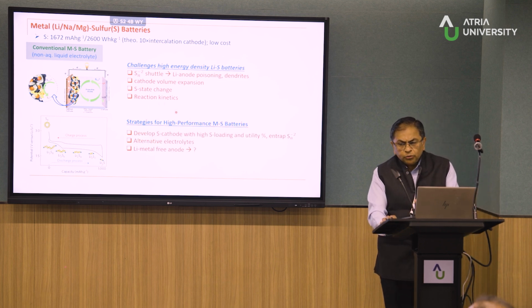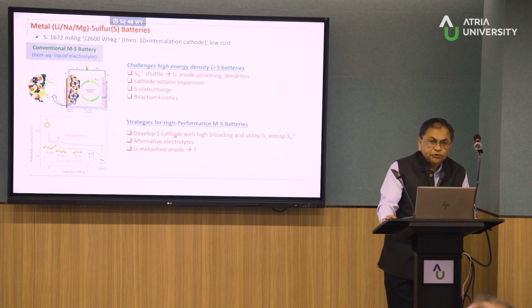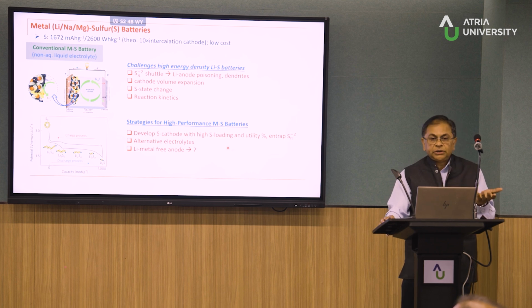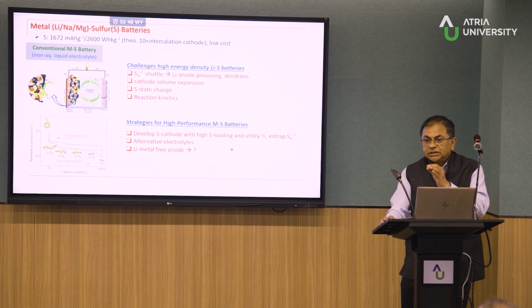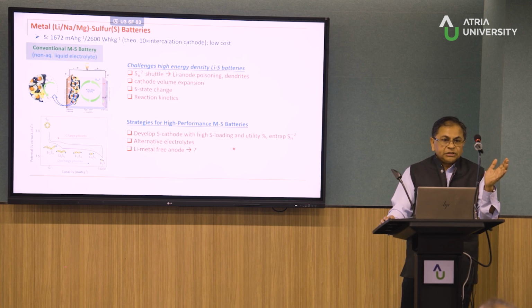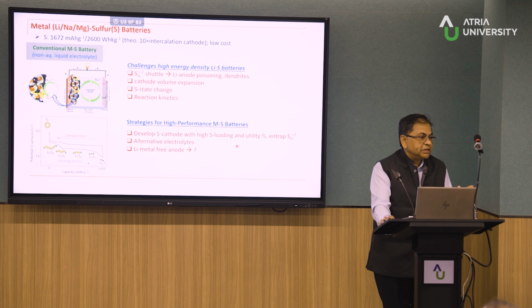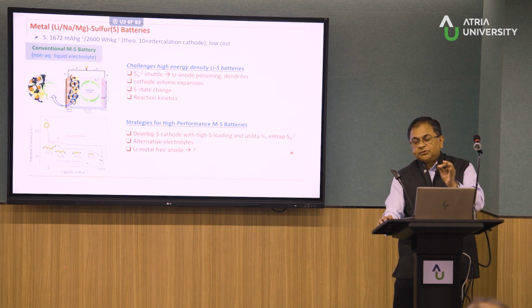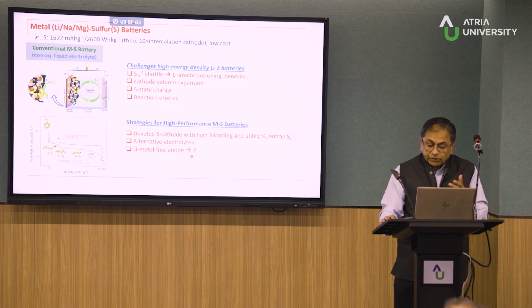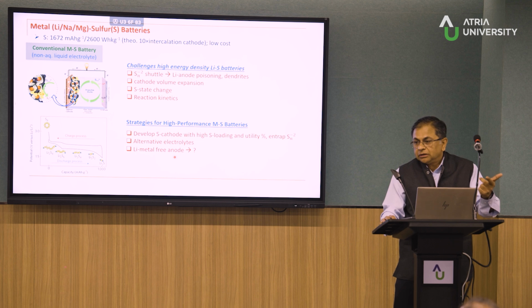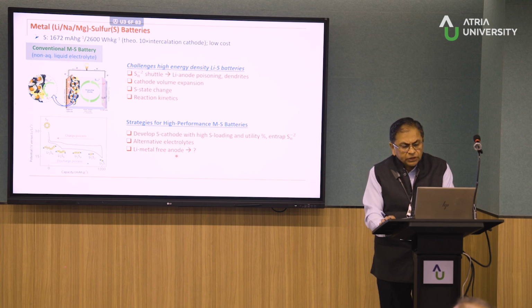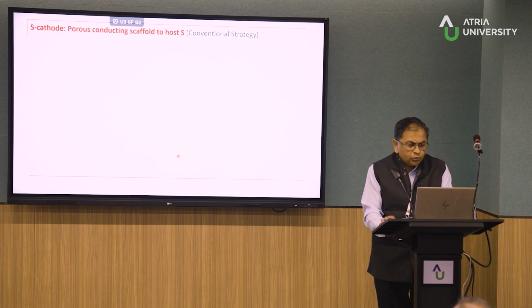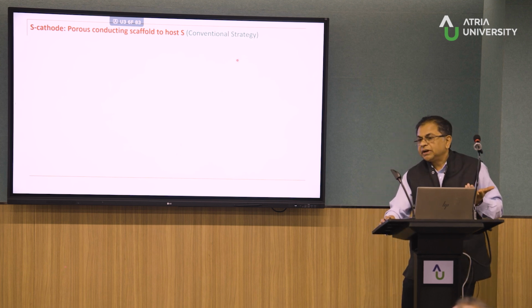Okay, so what could be the strategies here? Of course, we have worked on several fronts. One is you should have a very good sulfur cathode which can have a very high loading, and most important is the utility percentage. You can load 90% sulfur into a cathode, but if the utility is only 10%, that will give you a very poor capacity. And it should have on-site trapping of the polysulfide. All right. Look at alternative electrolytes. There have been strategies. Why work with lithium metal? Why not work with something which can lithiate it, or which can insert lithium and so on. So these are some of the strategies one looks at. So when we started a while ago, just like everyone, we adopted a conventional strategy, right?